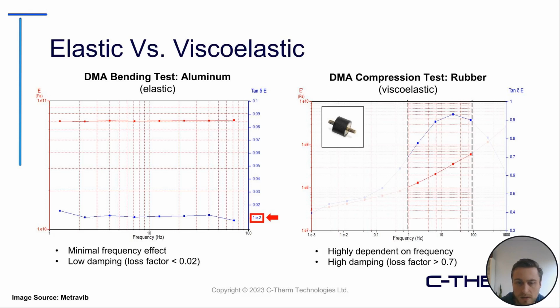And very low damping. I should note that all materials have a little bit of damping in them, but rubber and viscoelastic materials, composites too, all have a lot more damping compared to aluminum and other metals and elastic materials. When we look at the right, for that same frequency range, we can see that the rubber was highly dependent on frequency and had a very large amount of damping. This was just the previous example, zoomed in on the frequency range to be compared to the aluminum there.